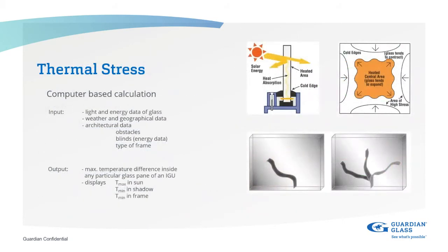Thermal stress. Again, thermal stress is becoming quite popular in this region, in particular for heat strengthened glass, and where we have spandrel glass and ceramic frit glass in spandrel areas. It's always worth considering that when you're looking at areas of high energy absorption, we run a thermal stress analysis. Usually for tempered glass, this is not the case, but for heat strengthened, especially in a ceramic spandrel area, we request that we run this thermal stress analysis.